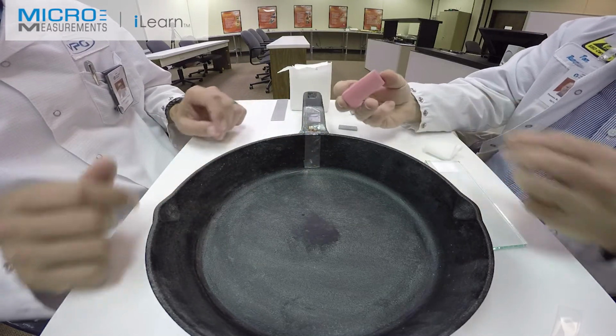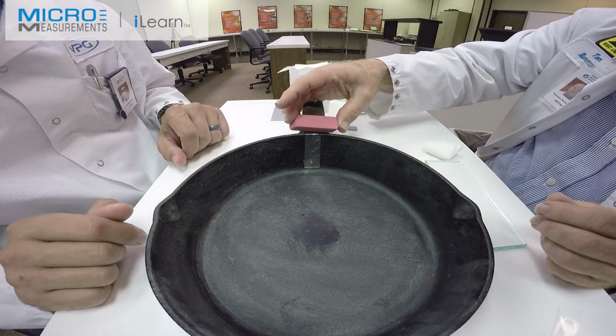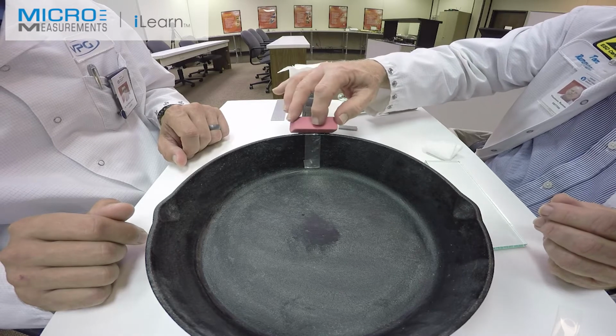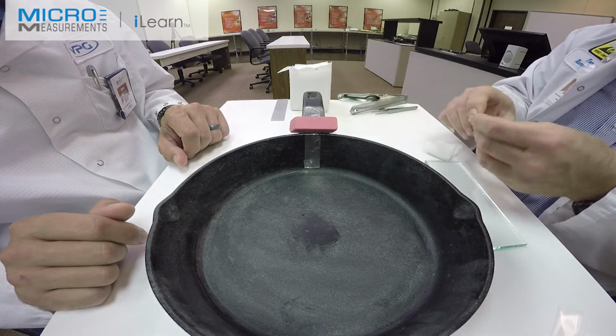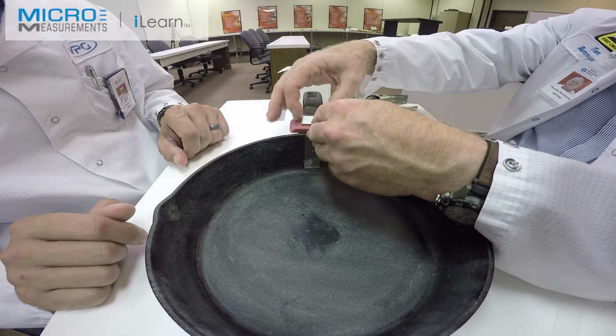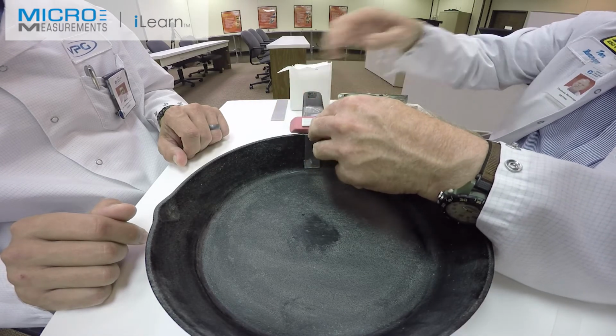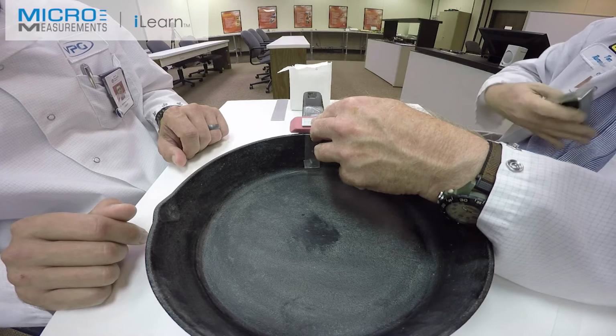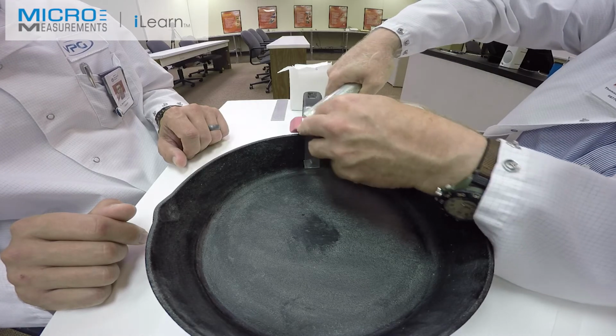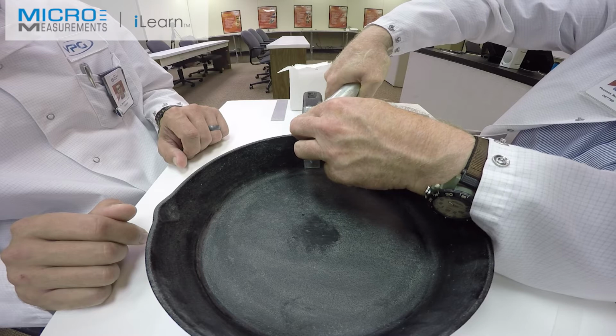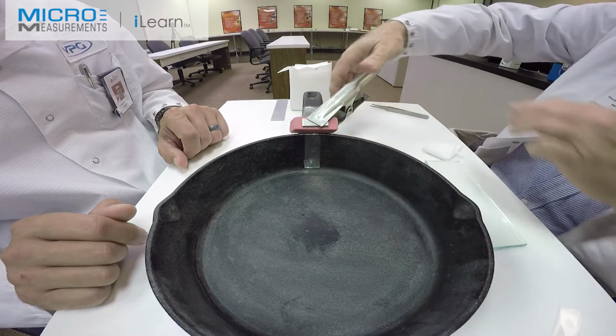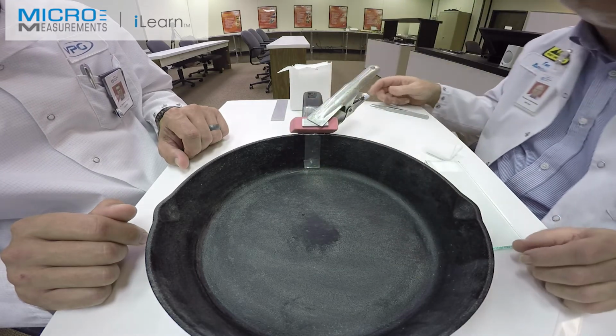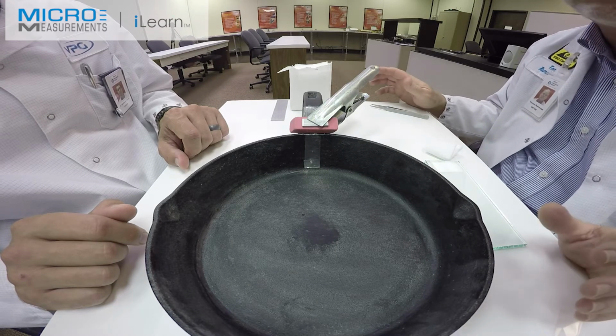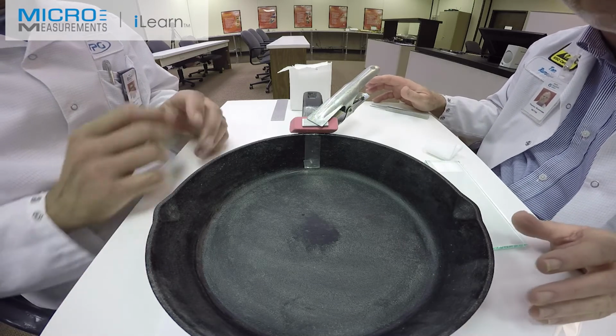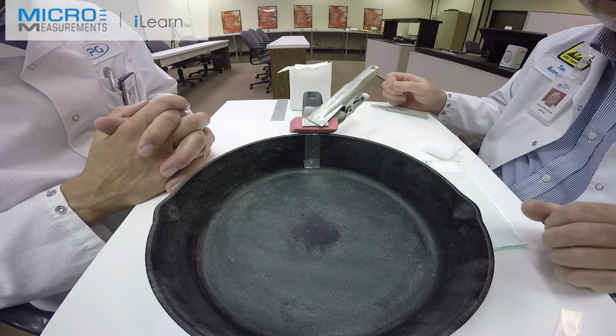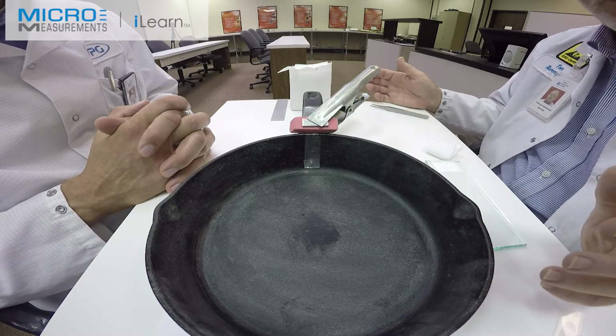We've taken this pink pearl eraser and we've formed it to the shape of the radius there so it fits nicely. We're going to put that over the top of the gauge and temperature sensor combination. The aluminum backing plate is to help distribute the load through the pink pearl eraser. I'm going to take a clamp, and this should be applying nominally around 15 psi of clamping pressure. And now we let it sit for a minimum of 6 hours, preferably 24 hours overnight or something like that. It gives you a guaranteed bond. And at this point, we wait.